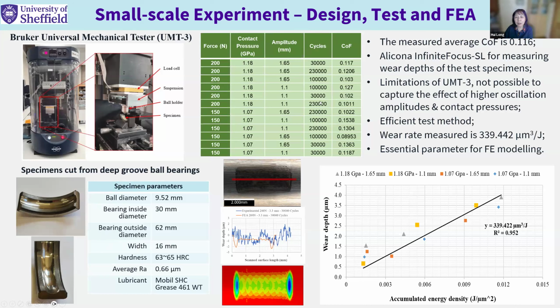This table shows all the tests conducted and some examples of measurements and the comparison between FEA and measured wear depths. The measured average frictional coefficient is quite low. We use Alicona to measure the wear depths. However, because of the limitations of this small rig, we are not able to capture the effect of higher oscillation amplitude and higher contact pressure. As you can see, contact pressure and amplitude are relatively small.